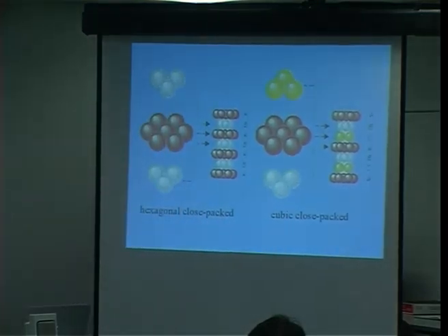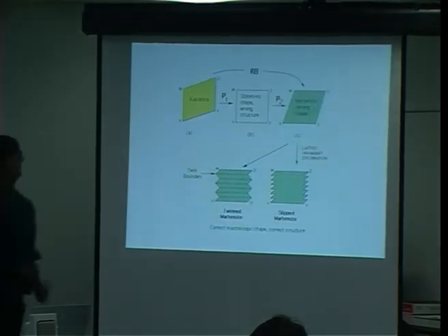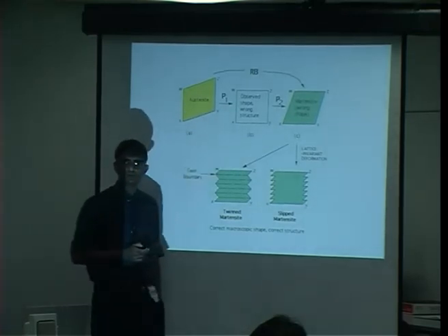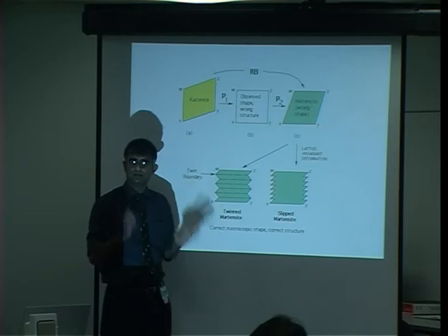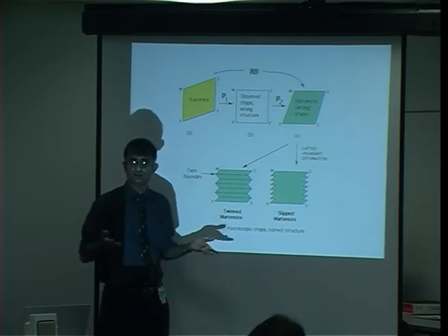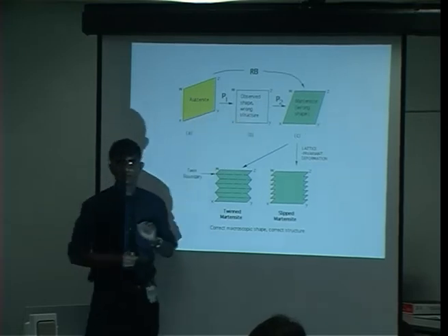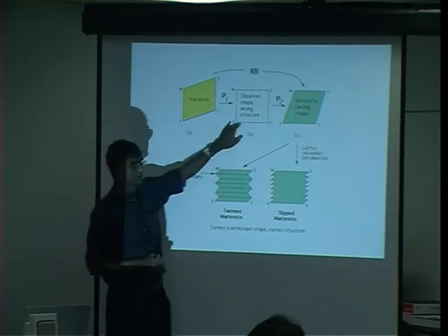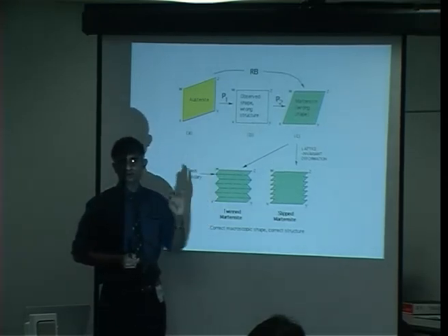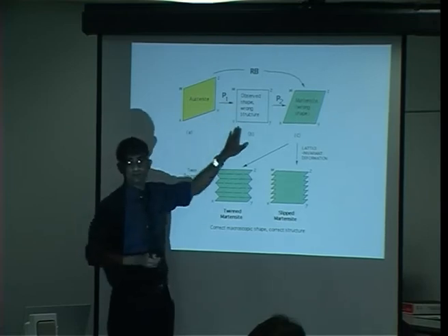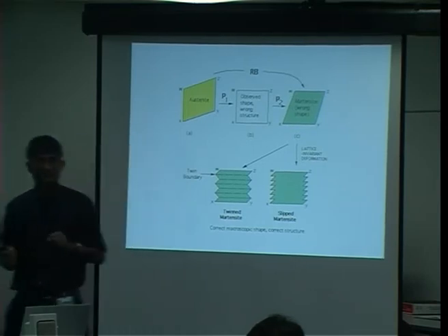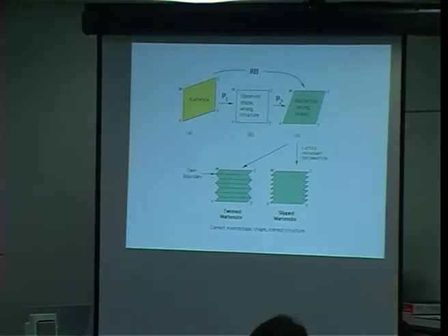So this is a much, much simpler martensite transformation, where if I go back, when I go from here to here, I get the correct structure and the correct observed deformation, because you only need a single shear to change austenite into hexagonal close-packed iron. So you will get a habit plane which is exactly 111 austenite, the plane on which the shear happens. There will be no twins and no steps in the interface, and that again is exactly what we observe.